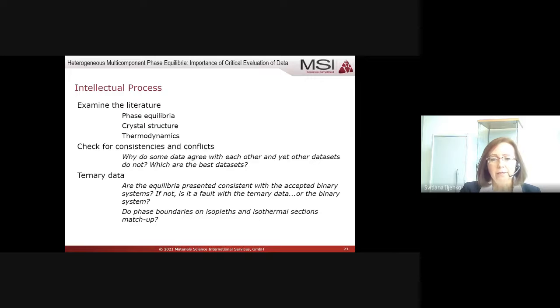And in the ternary data, of course, there is the problem with the binary system, which I also mentioned already. Sometimes we have to go to the binary systems in order to decide how to continue, if contradictions on the boundary borders of the ternary system appear between binaries and ternaries, or between different binaries which were accepted in the ternary and brought to these inconsistencies.